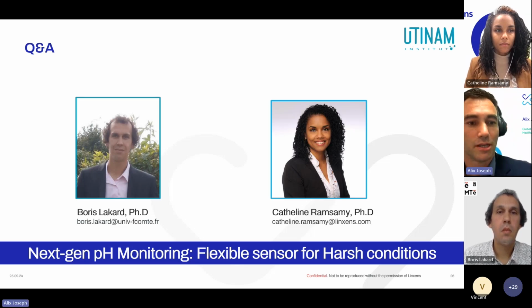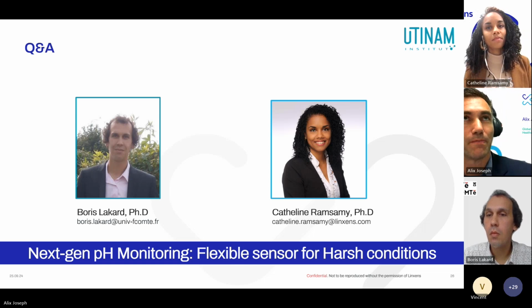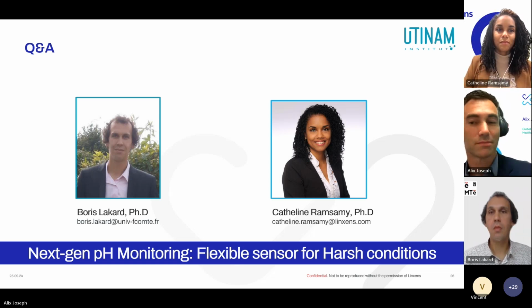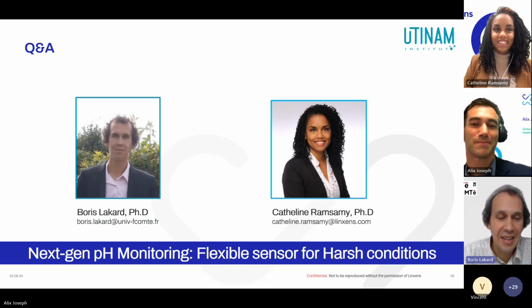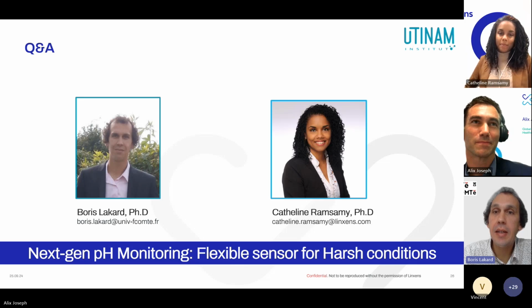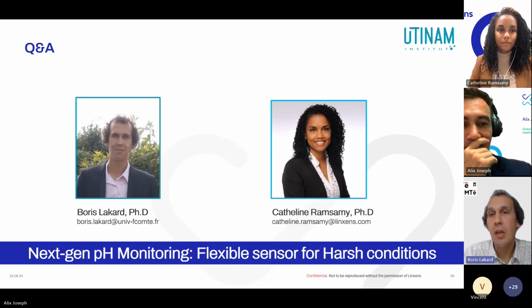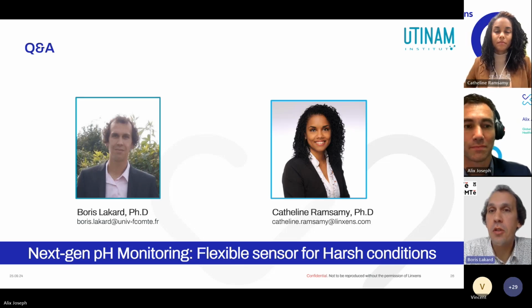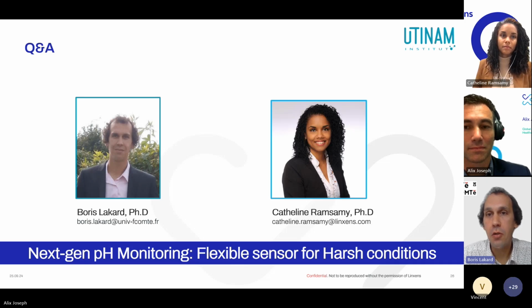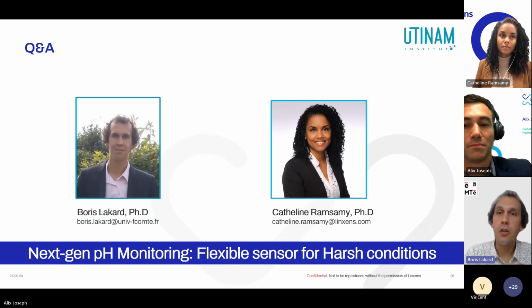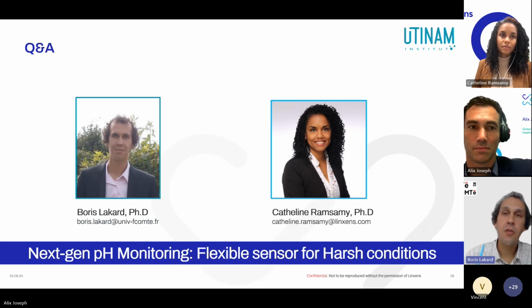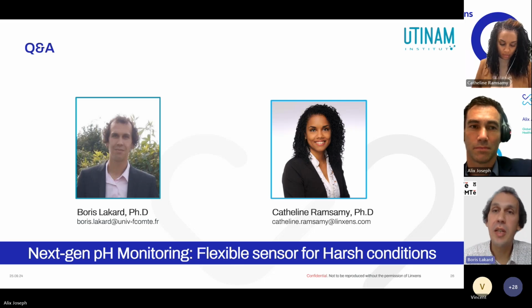Okay, another question. Does the sensor response depend on the morphology of the films? Boris, yes, I can respond. I think the response is highly dependent on the morphology of the films. When we performed the experiments in hypochlorite solution, we had a very compact and homogeneous film. And when you have such a film, you have a quick response and a reversible response. On the contrary, when you have something which is very porous, you can trap the species and the reversibility is more difficult to obtain. So yes, the morphology has a big importance.